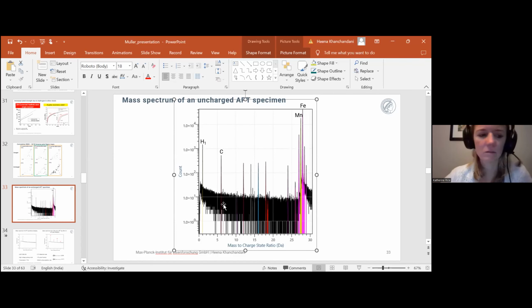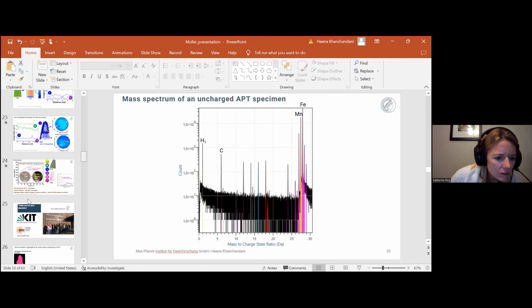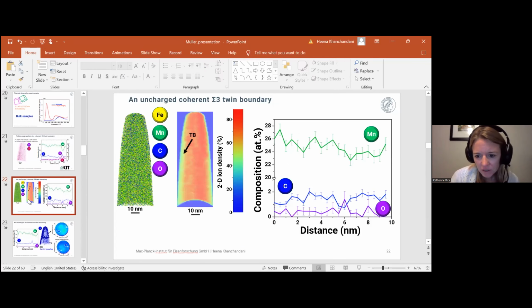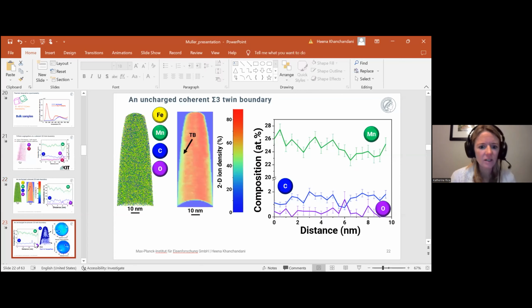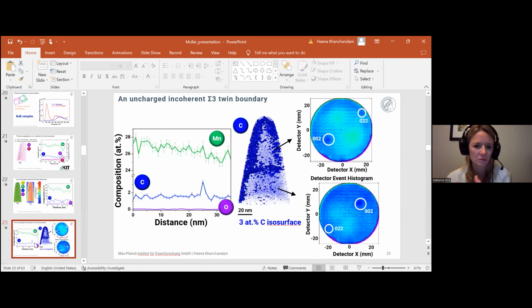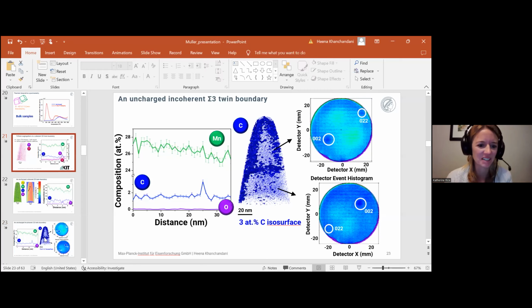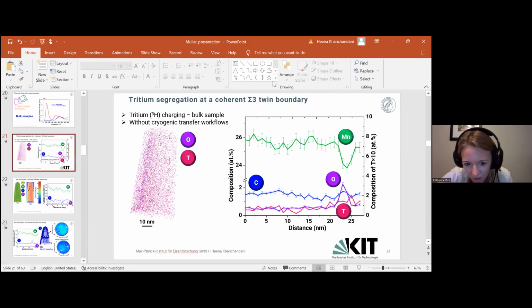I have a question about slide 22. This one, yeah. Actually, I think it's slide 23. Okay. So you're comparing this oxygen segregation to the results on slide 21 to show there's no segregation here for those oxygen species. For me, it's just difficult to compare because they're not on the same scale. So if you had plotted this on the scale of slide 21, what would that look like? Would the error bars be similar? To me, you have to kind of squint to see very low concentrations here with a rising trend.